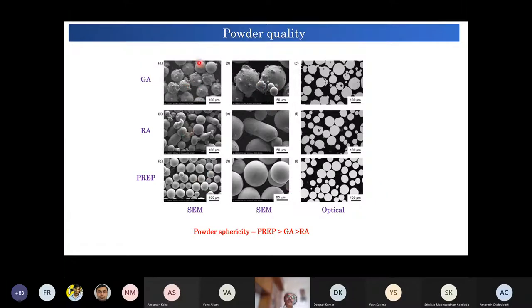Another thing is, one has to really optimize by electron microscopes, otherwise you won't be able to distinguish. For example, there is very little distinction if one examines the powder by optical methods. Very fine distinctions are there, so one has to really examine it by electron microscope to see what the powder size and morphology are. Here this powder is also appearing as circular or a little bit elliptical, but it is actually elliptical and it will create havoc in terms of densification.